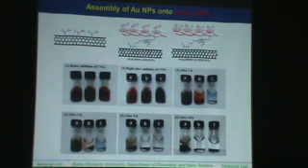Now we added in here the carboxylic acid functional CNT. B is ionic CNTs. C is imidazolium chloride functional CNTs. As we observed in the solution state, the color of these two ionic cases shows no change. Carboxylic acid also no change. But when you added the imidazolium chloride functional CNT, the color was dramatically changed to blue.